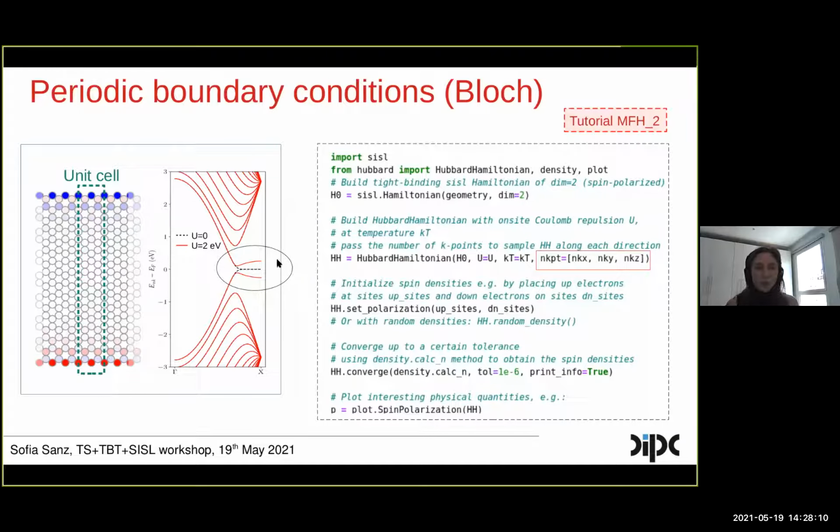That is the reason why the band structure of the polarized structure opens a band gap around the flat band area that belongs to the band structure for the unpolarized case. This band gap, which is called the correlation band gap, is proportional to the Coulomb repulsion parameter.